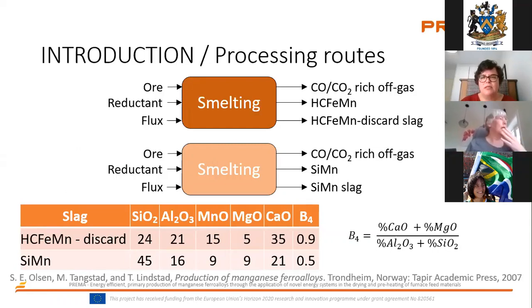In both instances, CO-rich off-gas is produced by the process. When you have an open furnace, the CO gas gets combusted on top of the burden. So the off-gas that's produced and cleaned afterwards is CO2 rich. In a closed furnace, the CO gas is captured and cleaned through a wet scrubbing system. The combusted gas is cleaned through a dry baghouse system. And then in both instances in South Africa, the slag gets discarded onto slag dumps.